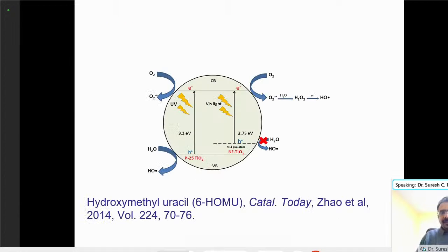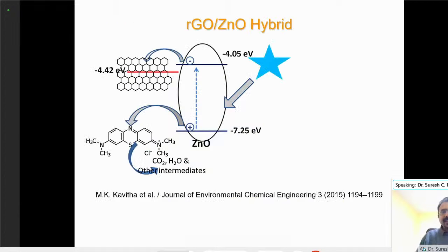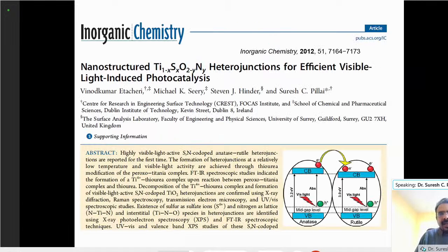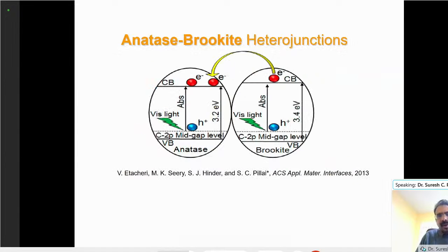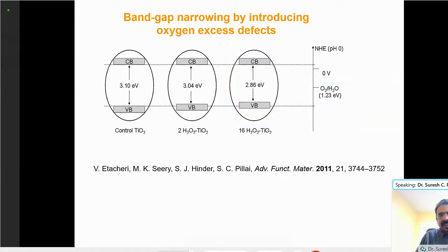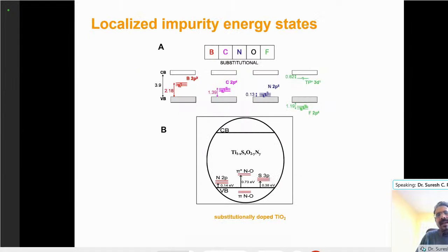Okay, so I'll finish in 5 minutes. These are some of the materials we have used: anatase-rutile heterostructures, anatase-brookite heterostructures, oxygen-rich titanium dioxide. We have developed a range of materials which can form additional energy levels in between the valence band and the conduction band. Look at this example, we have used nitrogen and sulfur doping.